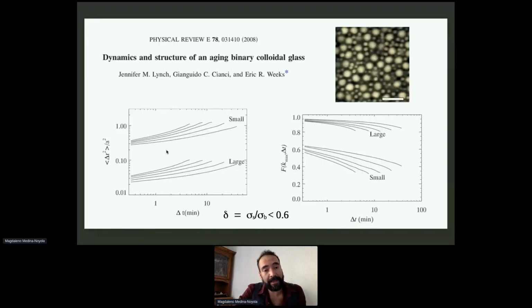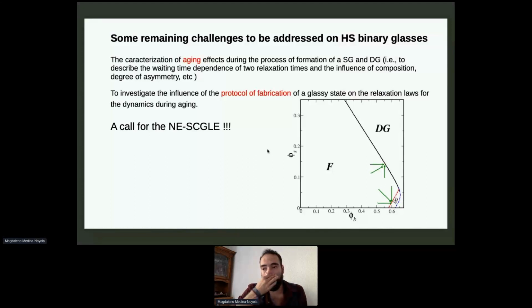This means describing these experimental facts. When one compresses the system to reach a glass transition, the mean square displacement evolves with time and develops these characteristic plateaus of the glassy state. And at the same time, variables such as the collective alpha relaxation time also evolve and become larger with waiting time, thus defining a non-equilibrium relaxation law for the collective dynamics. And this is an open challenge to be addressed. And I think there are not fundamental barriers, from my perspective, to address this problem using the non-equilibrium version of this theory for colloidal mixtures. But of course, there are a lot of technical details and a lot of work to be done.